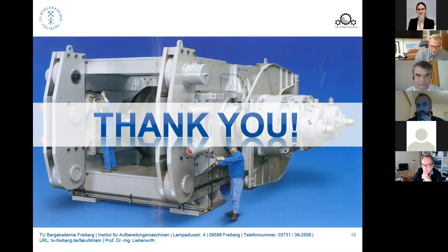With regard to the flotation, there have been quite a number of publications which indicated that you have an improved flotation. In 10 publications roundabout which we investigated, 8 of 10 were describing better flotation results, and 2 were describing a reduced recovery in flotation using this dry comminution. But in general, and this appears to me to be quite clear, if you don't have slurries where the particles are floating in, then you don't spoil the surfaces, and the flotation might certainly improve.